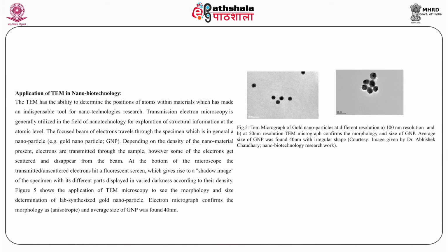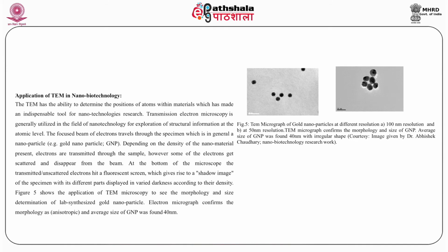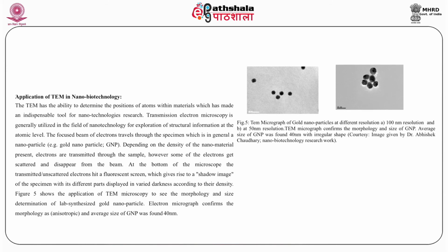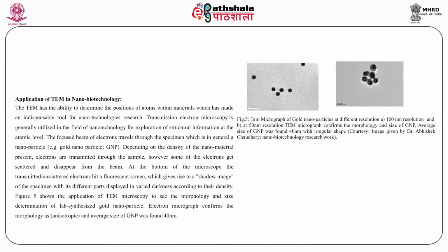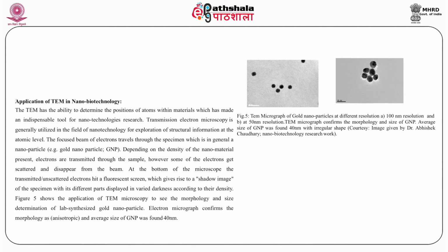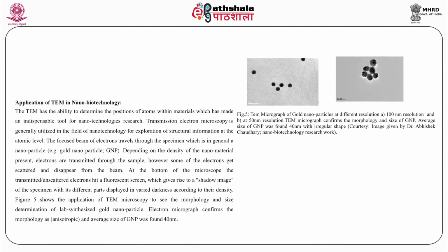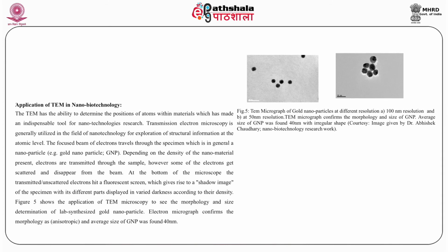This is another gold nanoparticle picture you can see on the screen with a different resolution, up to 100 nanometer and 50 nanometer resolution. So, the electron microscope confirms the morphology of the gold nanoparticles. The gold nanoparticle is about 40 nanometer with irregular shapes.